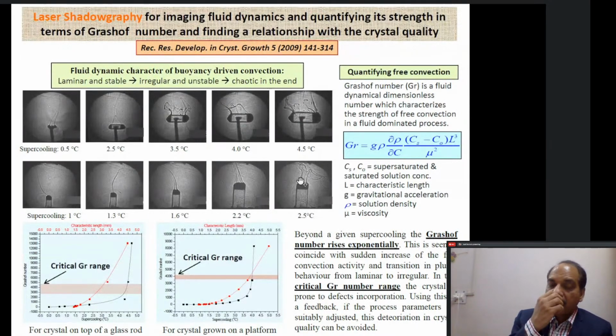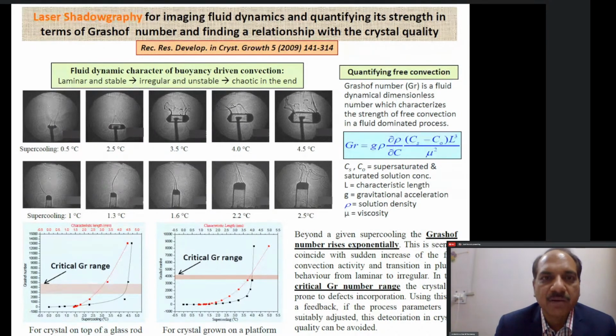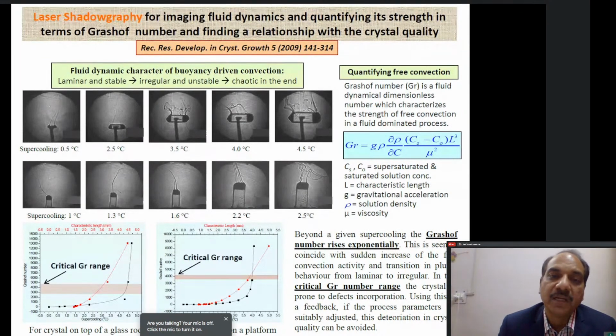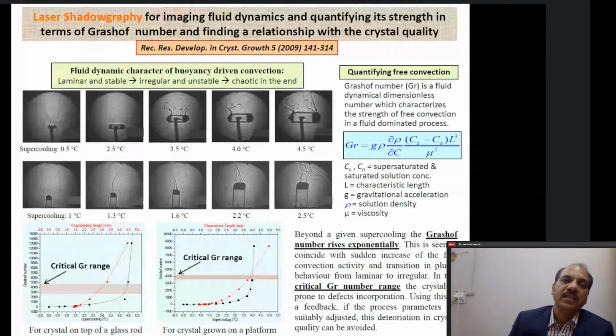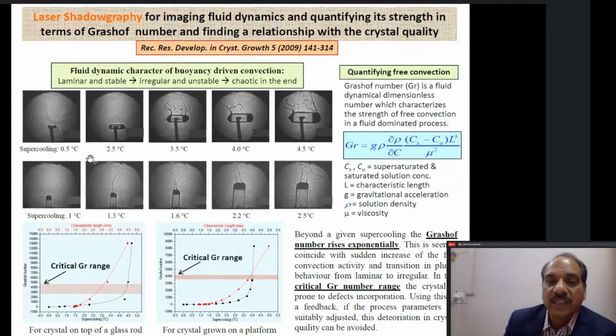And these plumes are what we record. And the fluid dynamic behavior of these plumes, whether the plumes are laminar and stable, whether they are irregular and unstable, or they are chaotic, gives us the information whether the crystal which is growing inside will be growing with good quality or whether it will pick up some defects. If the plume dynamics is such that they are chaotic, that is the stage when the crystal picks up a lot of inclusions. So we have to optimize the growth parameters in such a way, in an online manner, that we don't go to that condition wherein the plume behavior becomes chaotic. We want to work in the region which we refer to as laminar and stable, in which the crystal grows with absolutely nice quality. So this was as far as the qualitative discussion was concerned.